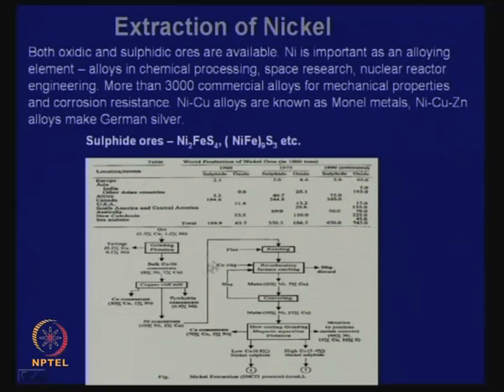Now, how do we proceed for extraction of nickel from sulfide? Here is a flow sheet called nickel extraction Inco. This Inco is a very famous company which is based in Canada, and you can see they are processing the nickel ores like this. Because they are sulfides, the ores will be like copper sulfide, very low grade. In this Inco ore, there is only 1.3% copper and 1.2% nickel, as low grade as that. They will be ground and there will be flotation. Tailings will lose a little bit of copper and nickel, but the bulk copper nickel concentrate will have 6% nickel and 7% copper. So, we get a bulk concentrate, we float both of them together.